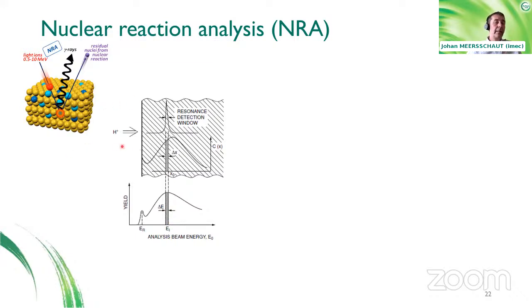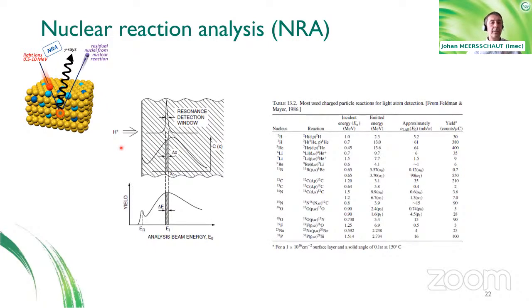So here I gave the example of hydrogen impinging on the sample. Depending on the energy and the particle type, you will excite different nuclear reactions. So for each isotope that you want to probe, you can select a different incoming particle or energy, and at the same time, you are very selective to that isotopic material. So by benefiting from isotopically enriching your sample, you can also look at specific regions of the sample.